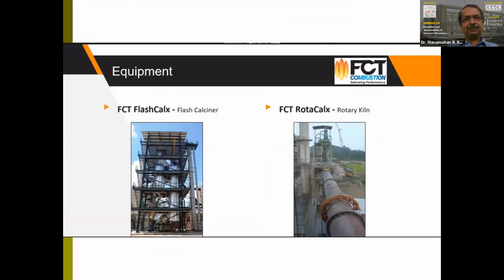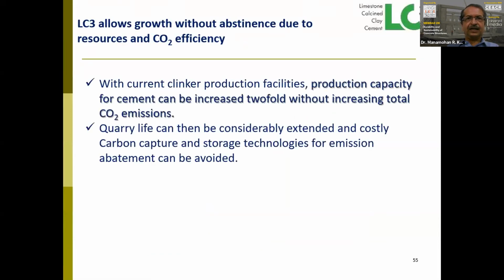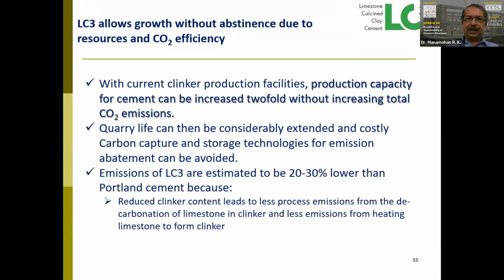So this calcination can be done using a flash calciner or a rotary kiln. That again depends on several pros and cons the cement company can look at and add on as a part of the cement company's production facility itself at various plant locations. So there are a lot of advantages in this. The production capacity for cement can be increased twofold without increasing the total carbon dioxide emission. Quarry life can be extended, costly carbon capture storage technologies can be avoided, and the emissions of LC3 are estimated to be 20 to 30% lower than that of Portland cement.